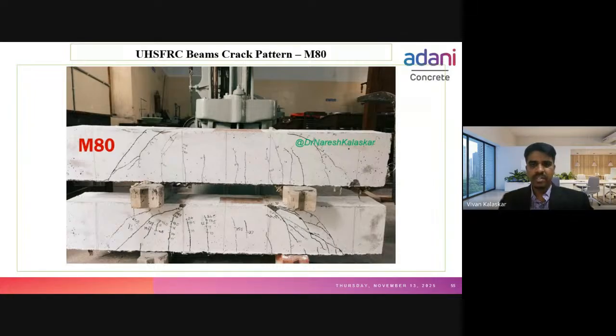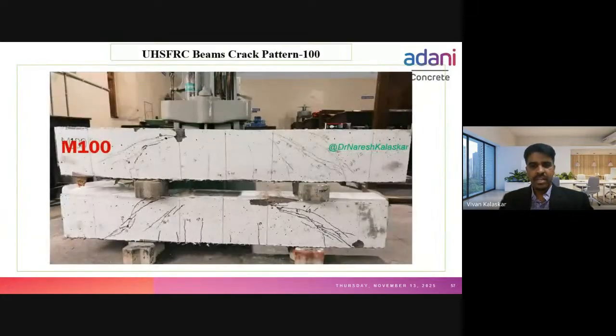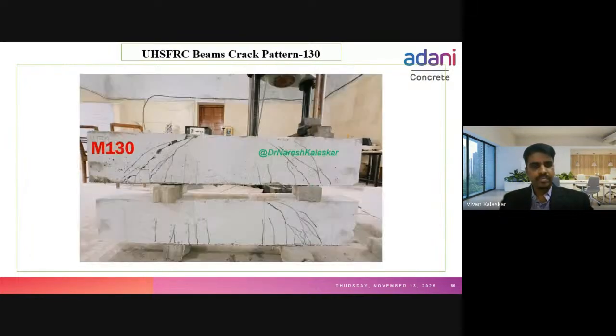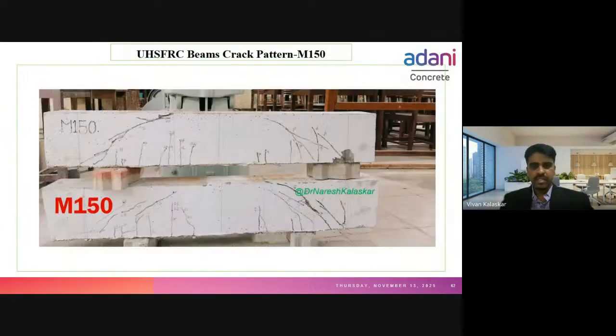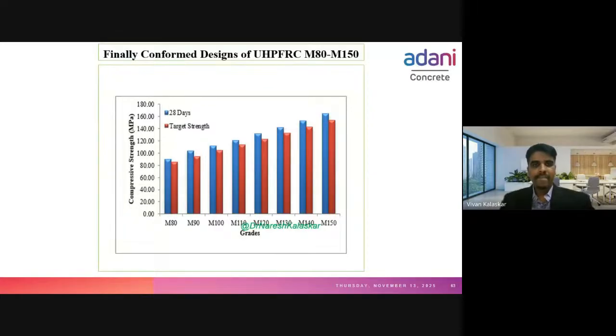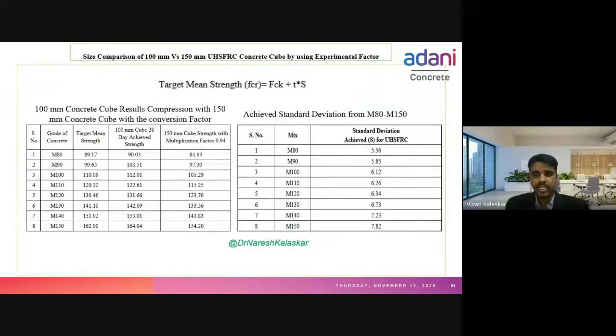These are a few photographs of beams which we have tested for M80, M90, M100, 110, 120, 130, 140, and 150. The details of this study will come in the next presentation, because it will take a minimum of 1 hour for this topic. Finally, when you compare with the target mean strength, all the designs from M80 to M150 with local materials have crossed the target mean strength, and all specimens have got exceptional results in mechanical properties, durability aspects, and fresh properties also. These are the target mean strength and standard deviation achieved from M80 to M150. The standard deviation has been established, and these are the size effect factors.